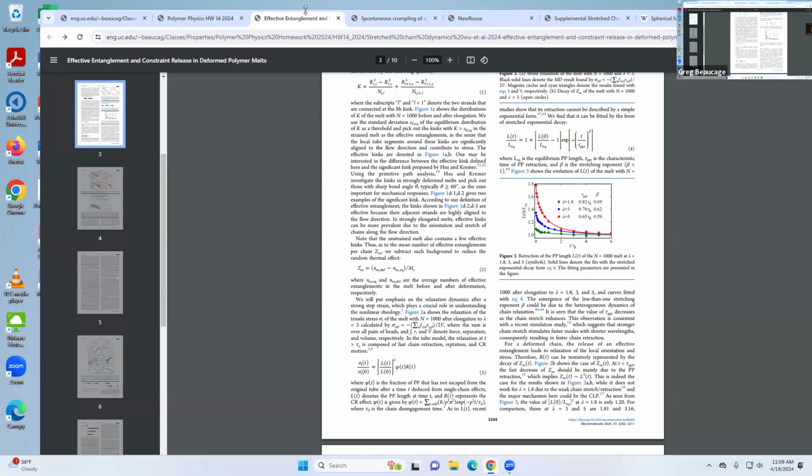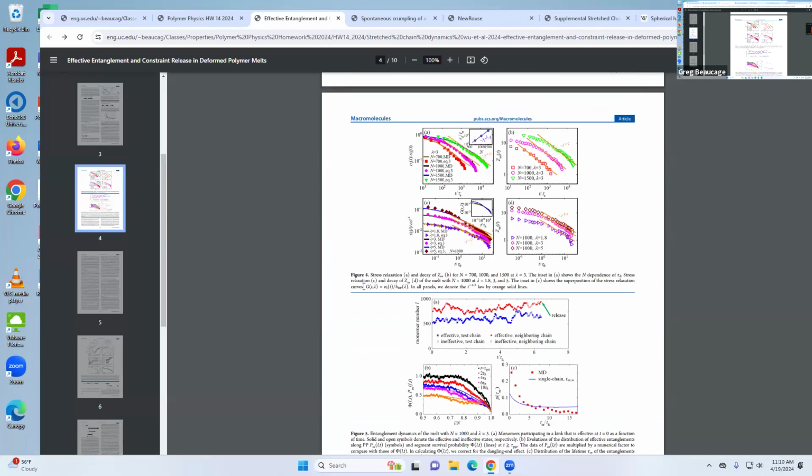Polystyrene, so they at least might have those bulky side groups. Yeah, the last thing with the neutron scattering is polystyrene. But he's using that because it has a convenient glass transition, so he can lock it in and doesn't have to keep his samples frozen. It would be difficult to keep them in liquid nitrogen, put them into the beam, and make sure the temperature didn't change. And polystyrene has a really well-defined rheological signature. The curves are really clean, and you can get it monodisperse, things like that. So he's using that for those reasons, I think.